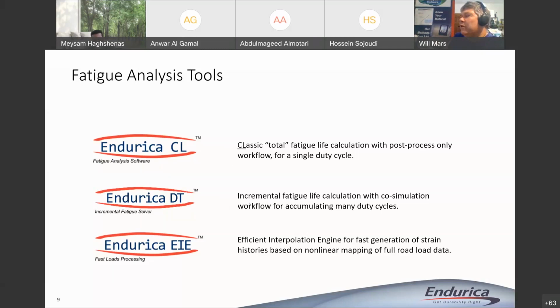This is the workflow that we would use when we have to accrue damage across different load cases, right? With CL, I can only have a single load case. With DT, I can make a schedule of cases, and I can accrue damage as you go further and further into the problem. DT also allows you to do a co-simulation, which means that you can sort of iterate between your finite element solver and your fatigue calculation, so that you can update stress strain fields based on how material properties are evolving as cycles accrue on the part. So those are things that we can do with DT.